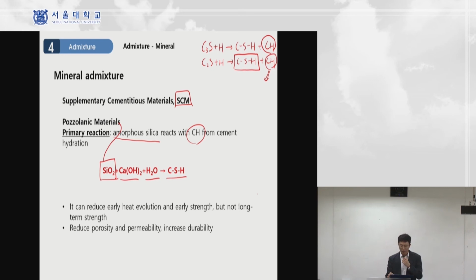Then what is the role of this calcium hydroxide here? Part of the calcium hydroxide produced from the cement hydration will dissolve in the water. Okay, so this is water, and this is crystal; some will stay stabilized as a crystal, but some will be dissolved in the water because we put water at the beginning. Water is a primary ingredient for making concrete. So it will decompose into Ca2+ and 2OH-, right? This is very important.